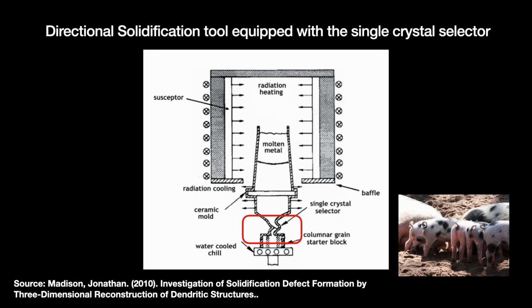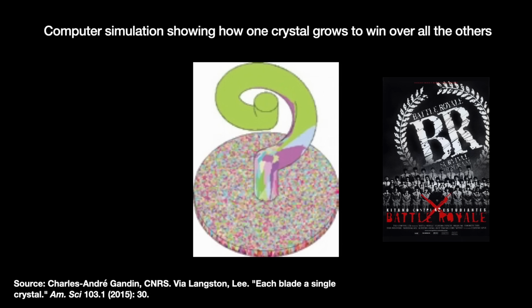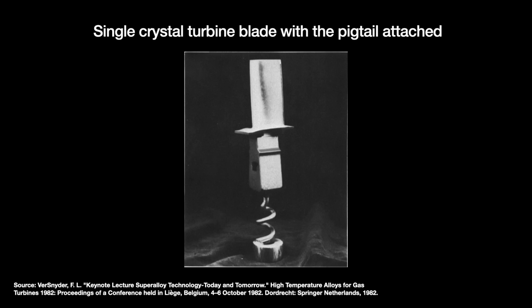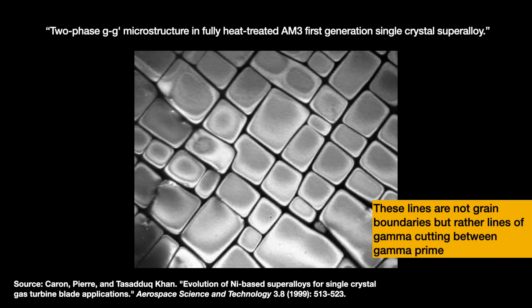Anyway, the pigtail takes in the growing columnar crystals and, through one or two turns, filters out all but the fastest growing single crystal. Then, as with regular directional solidification, we slowly move the melt downwards. That winning crystal exits the pigtail and eventually expands to crystallize throughout all the melt in the whole mold. The result, if done right, is a turbine blade arranged into just one single crystal. No grain boundaries. Though I want to note that though the atomic lattice is unbroken, the crystal itself is not homogeneous. You still need those phases, those gamma and gamma primes, to add strength, which explains why they might still look like they have grain boundaries. Anyway, single crystal processing was a game changer.